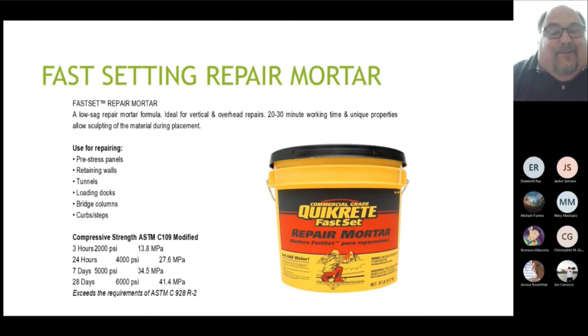One important thing you should know is that anytime you have added acrylic fortifier, which we'll talk about a couple of slides from now, you don't want to damp cure it. Air is important to the curing process with acrylic fortifier. I'll get into that more later, but any other time you're curing these products, you just want to damp cure them, mist them, fog them with some water for the first 24 hours.